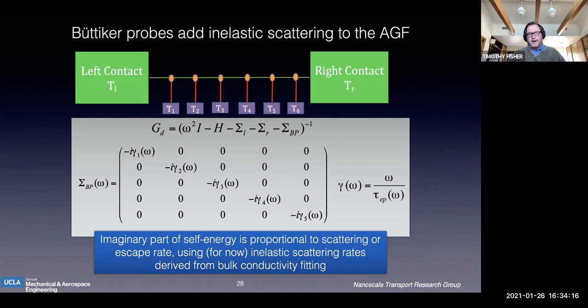And those electron-phonon interactions are mediated by these little purple things called Büttiker probes. And so this is something that physicists have been doing for a long, long time. And so we put those into the code with appropriate scattering models. And so part of the DFT does give you that. It kind of gives you those gammas that you see here that will make a self-energy matrix for the Büttiker probes. Again, it's a little bit in the weeds, but it's still what I consider to be a basic principles approach as opposed to fitting.